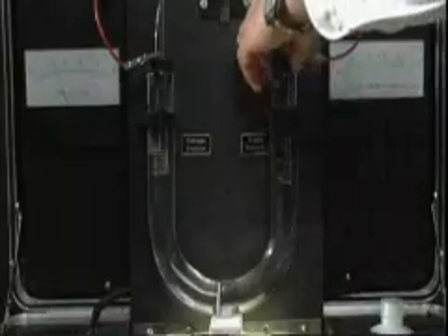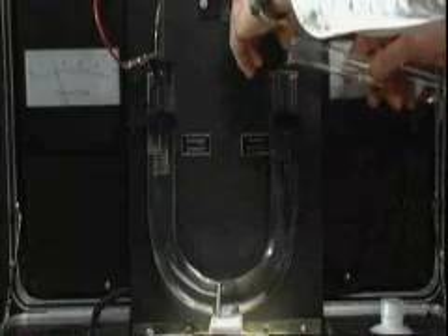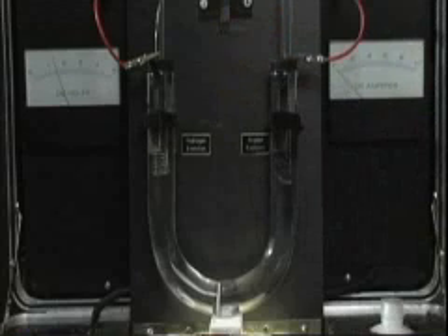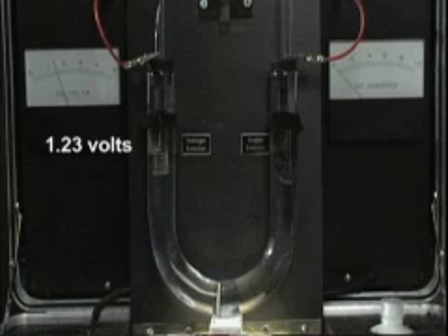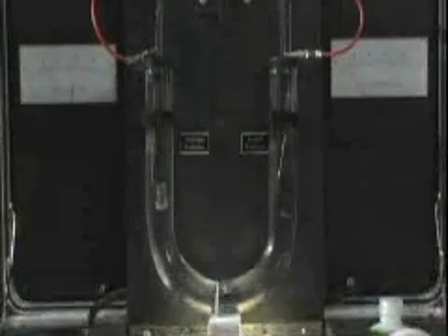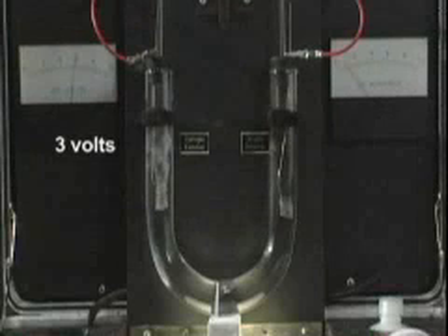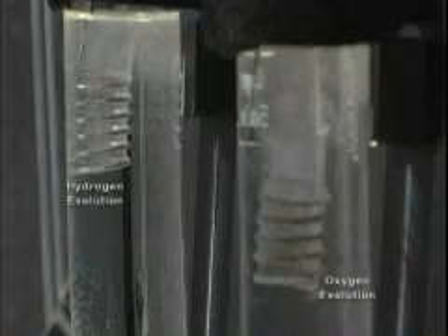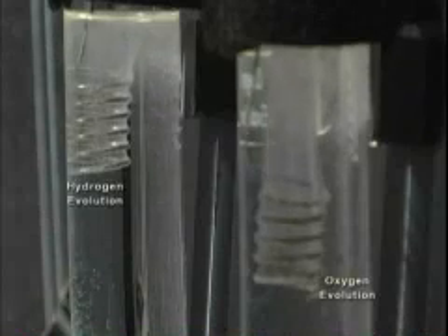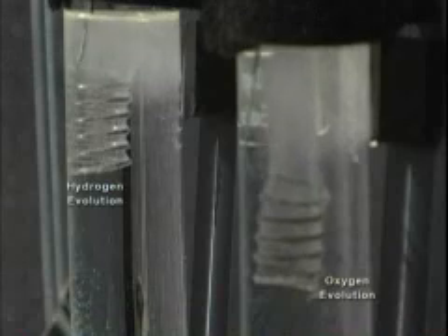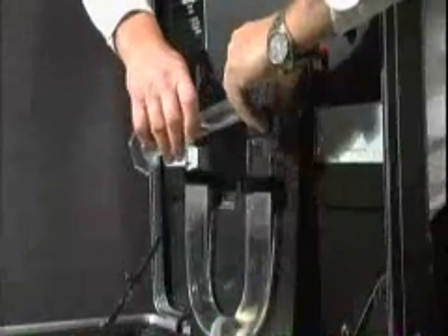Next, I will add some concentrated potassium hydroxide to both compartments. Potassium hydroxide is a very good conductor. Again, at 1.23 volts, we still see no observable evolution of gas. However, as we raise the voltage to 3 volts, vigorous gas evolution is observed at both electrodes. The additional voltage above 1.23 volts is consumed by a combination of internal resistance in the electrolyte and in activation of the oxygen electrode. Finally, I will add methanol to the oxygen electrode compartment.